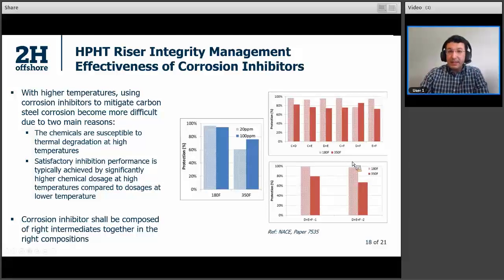And the second plot shows that you need to select the right chemical intermediates to come up with a good composition for the corrosion inhibitor. Even if you get the right intermediates, the composition is important. This plot shows you have D, E, F, the same chemicals, for composition one, and D, E, F, the same chemicals, for composition two. The same chemical elements but different compositions will give you different protection. So you have to be careful with that as well. The right chemicals in the right compositions are very crucial for corrosion inhibitors in the high temperature region.